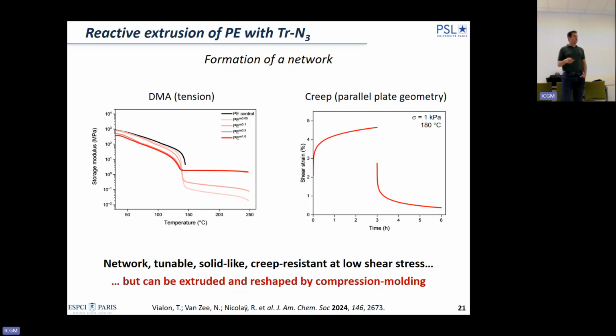a small percentage, which led us to believe, and we did other things, that the crosslinks we create are of two types. There are first physical crosslinks based on dipolar interaction and van der Waals interaction. And also we create crosslinks which are polyazine, but this polyazine bond, we believe, can be thermomechanically activated. At high temperature and/or under sufficient stress, they break and reform.